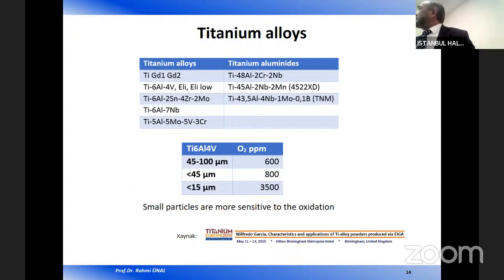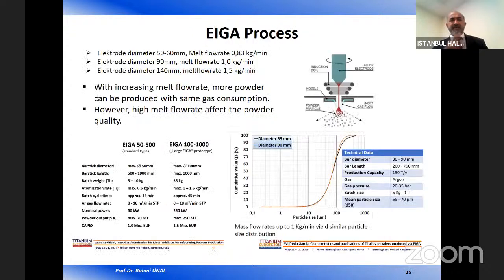Let's look at the oxygen level for some size ranges. If the powder is less than 15 micrometers in size, it has 3,500 ppm oxygen. Less than 45 micrometers, it is 800, and if the powder size is greater than this value, it can have 600 ppm oxygen level. We can easily say that small particles are more sensitive to oxidation.